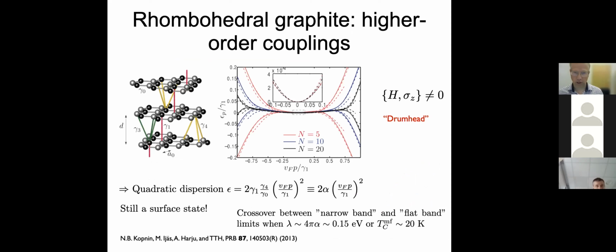Now, what I presented before was based on a model where I only take the strongest coupling between the layers, this gamma 1 coupling. In reality, there are also other couplings, gamma 3, gamma 4, and so on. We have made a DFT study of the surface spectrum, and what we find is that you still have a surface state in the presence of these other couplings, but instead of a flat band, you have a quadratic dispersion. Which means that you essentially have a narrow band.